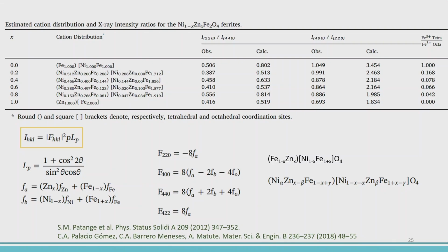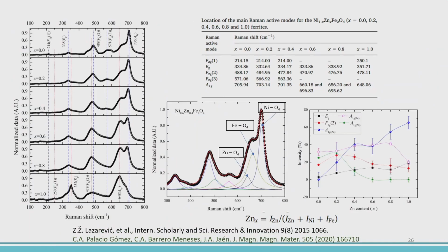Again, here it is very important that we use this formula based on this cationic distribution, but if we assume another cationic distribution, then this formula changes. You have to take care of that, and then we compare the theoretical and calculated for some lines that are reported that are sensitive to the cationic distribution. Some lines are good, some are not good.